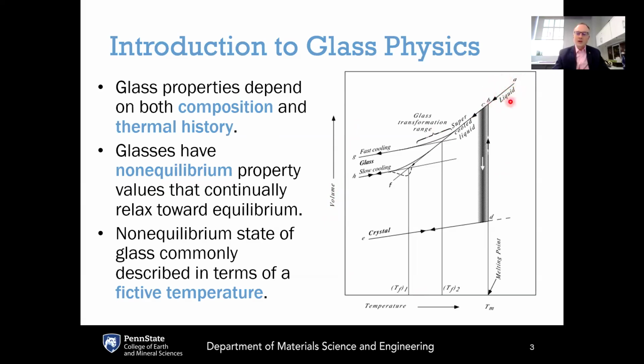So if we start up here in the upper right corner at high temperatures and high volumes, this is a liquid. And if you cool the liquid below its freezing point, if the liquid were to stay in equilibrium, it would crystallize. And so it would undergo a first order thermodynamic phase transition, going from this liquid line down to the crystal line. And then any continued cooling of the crystal would mean that it would follow this crystal line here at the bottom.